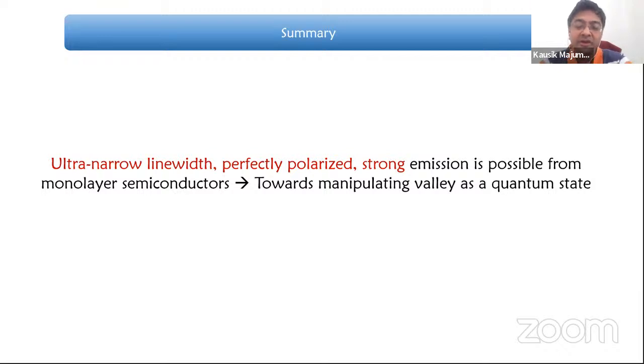Yeah. Right. So interlayer excitons are significantly slow. It can depend on how well matched they are, let's say you have the same chalcogen, then they are sort of well matched. But if you have different chalcogens, the lattice matches are different. That's one thing. Secondly, there could be a twist angle, right? So depending on these, that will actually destroy the valley. That may destroy them. Right.